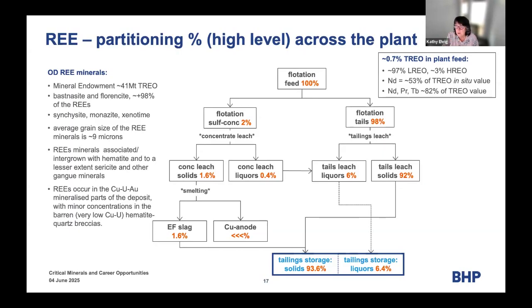It's frankly not worth it to do that because we have a recycling load, and as soon as you drop that down, it goes down quite a bit. We'll drop down to the blue box in a minute, but on the right-hand side, the sulfide flotation concentrate, yep, 2% of rare earths go in that.